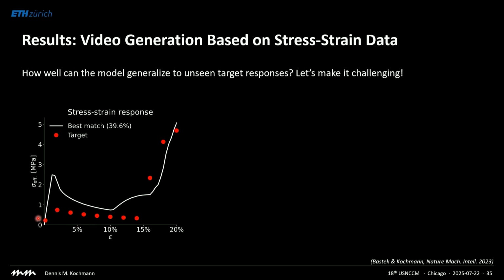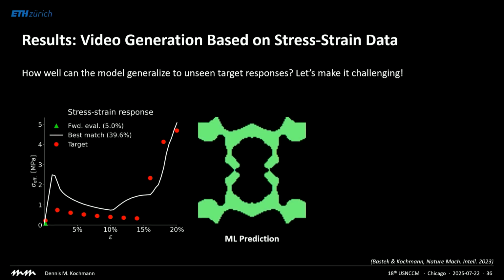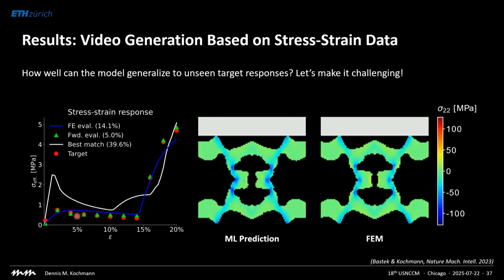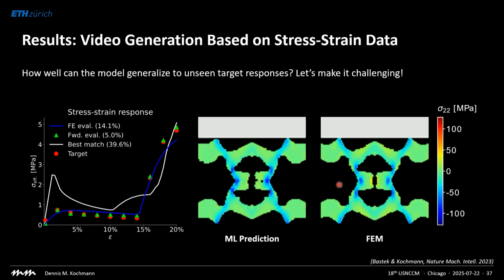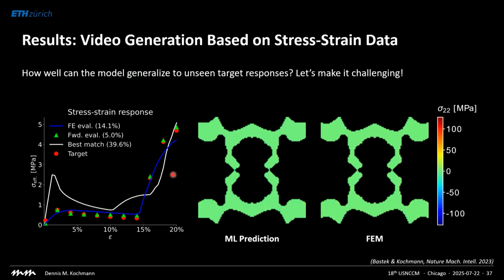So here's an example. The red dots are the stress-strain response that we wanted. We wanted to make it challenging by having something that's first soft, and then it hardens dramatically. If you look through the 53,000 samples in the training set, the white line is the best match we could find. If we use the diffusion model, it shows us this structure and this video, and it tells us that the stress-strain response is the green over here. Now, we can't really trust this, but we can take the structure, put it into a finite element software, and see what it really is. And what we get is the blue line in the simulation on the right. And if you look at the stress-strain distributions and the curve over here, they match beautifully exactly what we wanted.